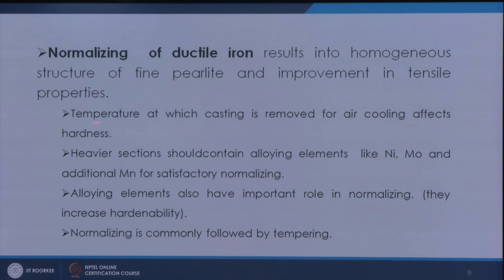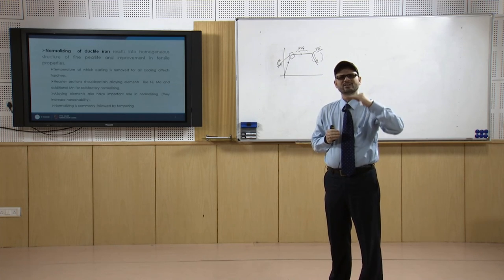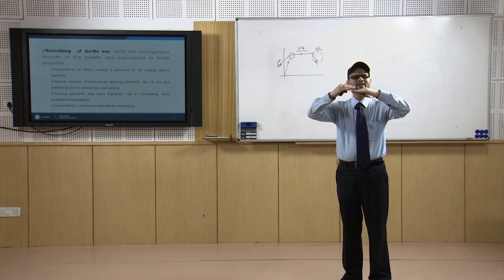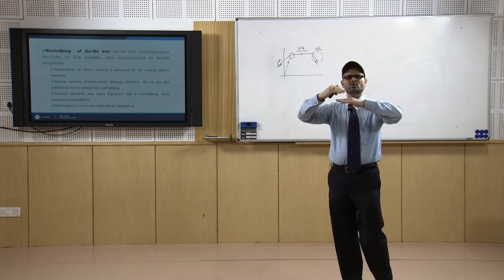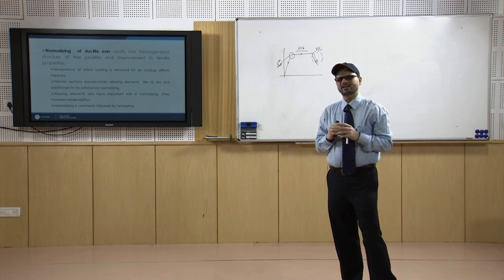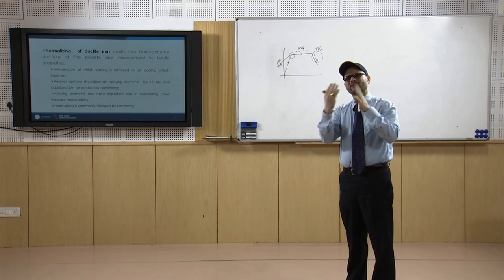The temperature at which the casting is removed for air cooling affects the hardness. If you are removing the casting and letting it into air below 850 degree C, that will affect the hardness. So you have to maintain a temperature. You must not go below a certain temperature, somewhere like 850 degree centigrade. So that temperature is one of the parameters at which you have to take it from the furnace and allow it to cool in the air.